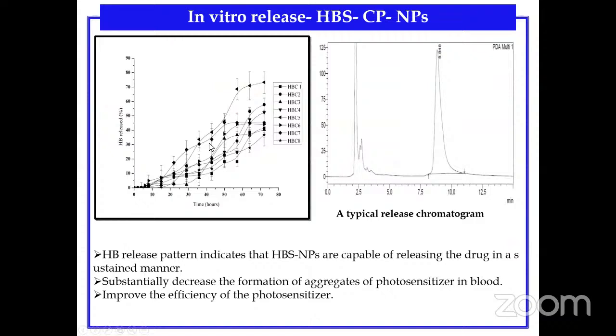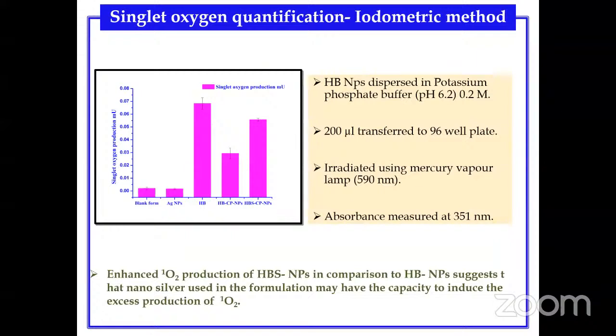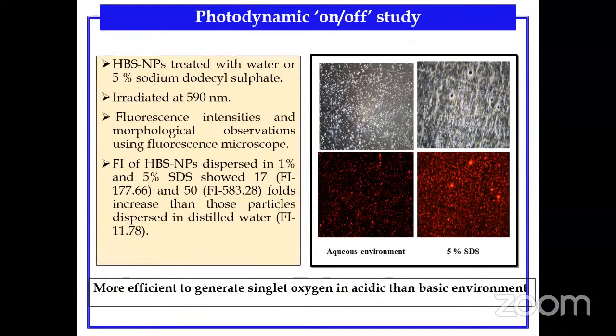We also studied drug release for 72 hours, wherein we were able to get delayed drug release. So that indicates that at different time points, we can trigger the release of the drugs. So we found what could be the optimum concentration of dose that can be given without quenching effect. When you increase the concentration of those particles, it will produce an increase in singlet oxygen production, and at a certain point it will also produce a quenching effect.